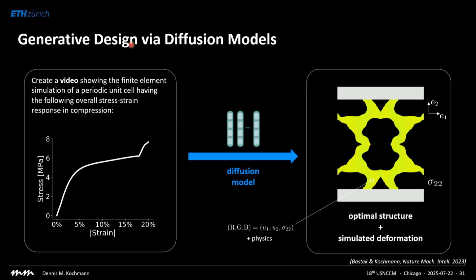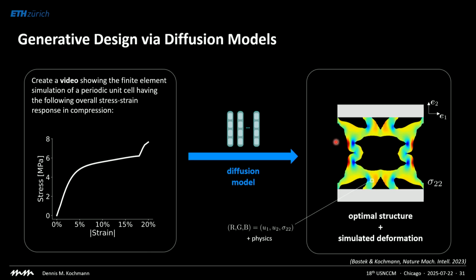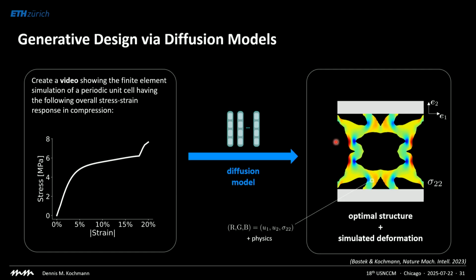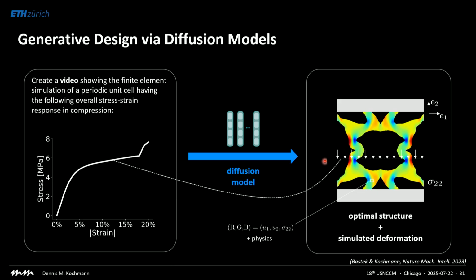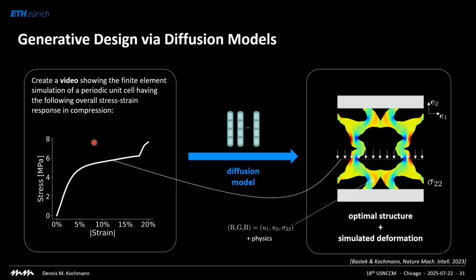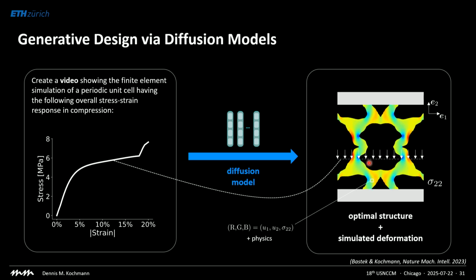Well, we can use the original scheme. Every video has RGB channels, red, green, and blue. We override those with the horizontal and vertical displacement components and the stress in the vertical direction, because that's what we care about. And we can even build in physics, which is very important here. For example, I know that the sum of all sigma vertical components in any row must match the effective response, because this is the homogenized response. I also know, if this is quasi-static, that the sum of all the vertical stresses at every single row must be the same. So I can build in physical constraints.